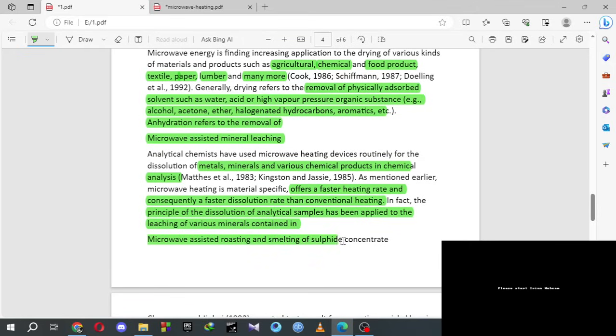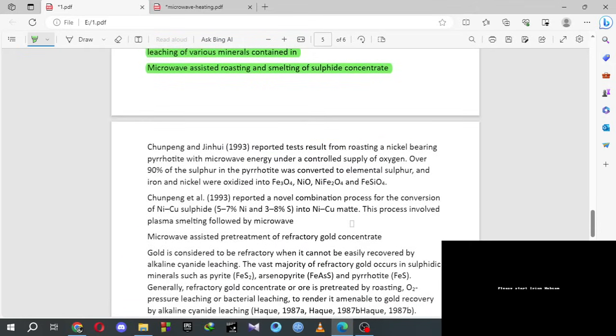Microwave assisted roasting and smelting of sulfide concentrate. Researchers reported test results from roasting a nickel bearing pyrrhotite with microwave energy under controlled supply of oxygen. Over 90% of the sulfur in the pyrrhotite was converted to elemental sulfur, and iron and nickel were oxidized into ferrous oxide, nickel oxide, nickel ferrous oxide, and nickel sulfur oxide.